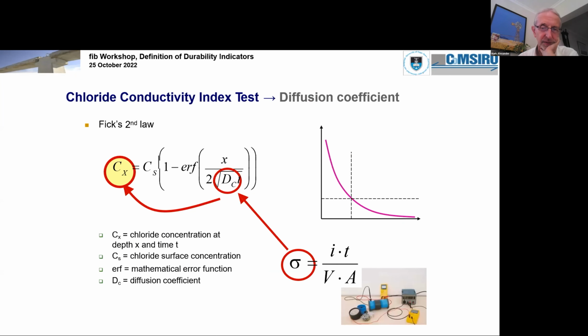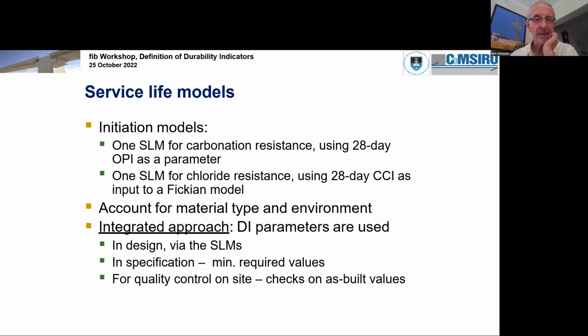And again, using the very well-known Fick's second law, the chloride conductivity is linked to the diffusion coefficient. And then knowing the surface concentration, we can work back to a chloride value and therefore a chloride profile. And in that way, one can start to understand what's going on. And one can also use it, of course, for quality control by limiting that chloride conductivity index in the structure itself. And so that leads on to the models that have been developed.